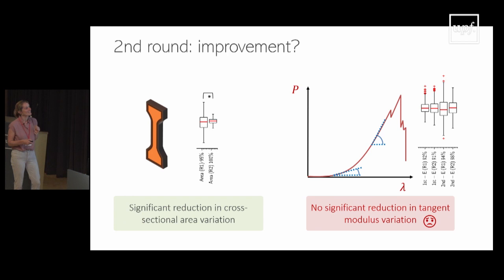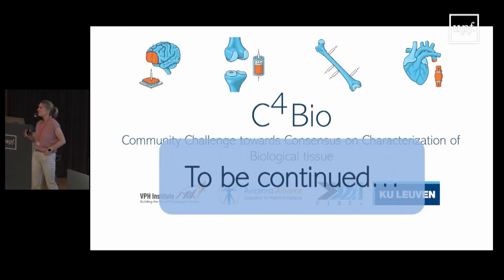But what we really wanted to have a reduction in were these tangent moduli, and here there was simply no significant reduction in the tangent moduli between the different research groups. So everybody was actually just really disappointed. And actually, well, it's not always nice to bring bad news, but that's where we're at right now. So we are in a very disappointed phase, and we really need to do something about this.